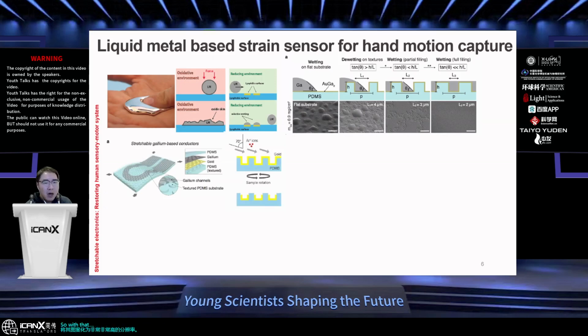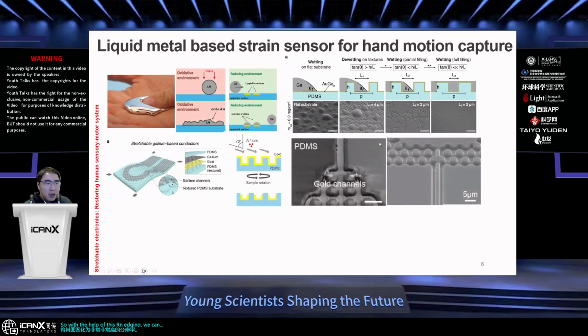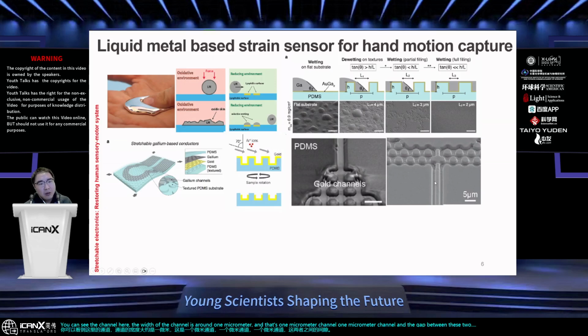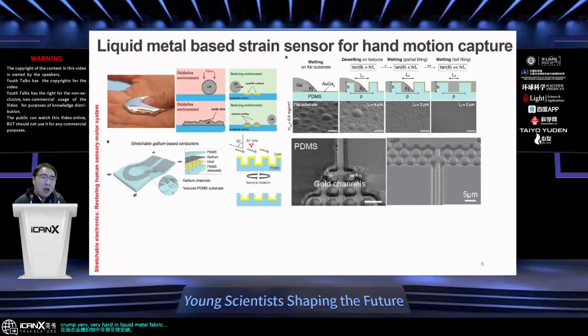With the help of ion etching, we can achieve this. I'm not sure you can see my mouse on the screen, but you can see the channel here. The width of the channel is around 1 micrometer, and the gap between two channels is 2 micrometers. In this way, we prove that we are able to fabricate liquid metal at a resolution of 1 micrometer, which is very high for liquid metal fabrication. Further on, with e-beam lithography, the resolution can even be improved.